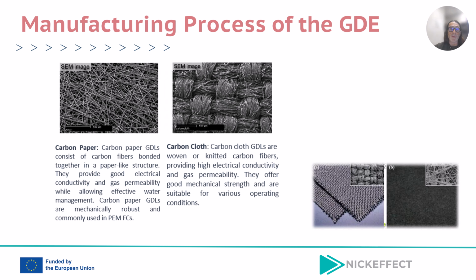On the right, we see carbon cloth shown both in a SEM image and as a physical sample. Carbon cloth is made from woven or knitted carbon fibers, giving high electrical conductivity, strong gas permeability, and good mechanical strength. It is well suited for a variety of operating conditions and is often used where flexibility and durability are needed.